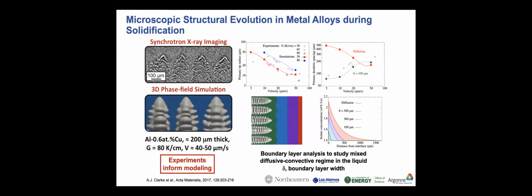So one of the benefits of these kinds of experiments is we can pull out quantitative information about what we're seeing. This is an example snapshot of dendrites from our synchrotron X-ray imaging, and we can pull out characteristics about the microstructure. For example, the primary tip radius, or the spacing of these features, the primary dendrite spacing, which could correlate to something like strength of a material, or for example, secondary dendrite arm spacing has been correlated to fatigue performance of materials. So we can pull out these quantitative characteristics.